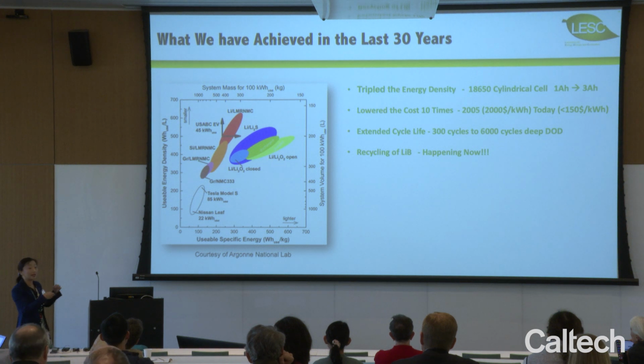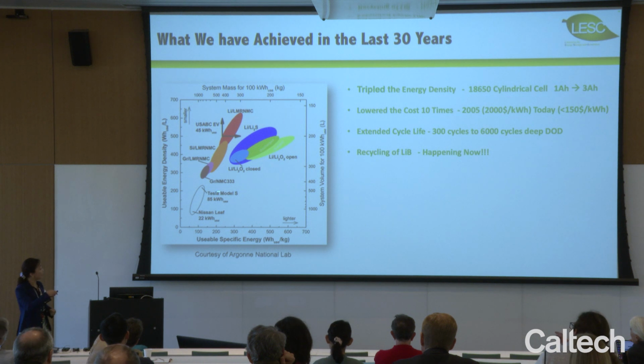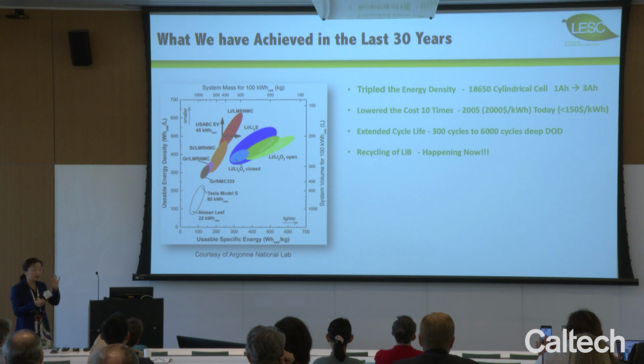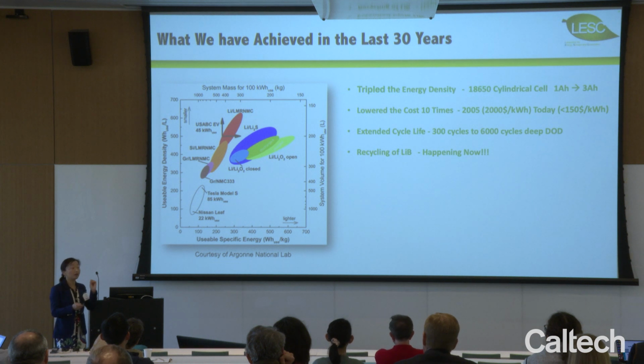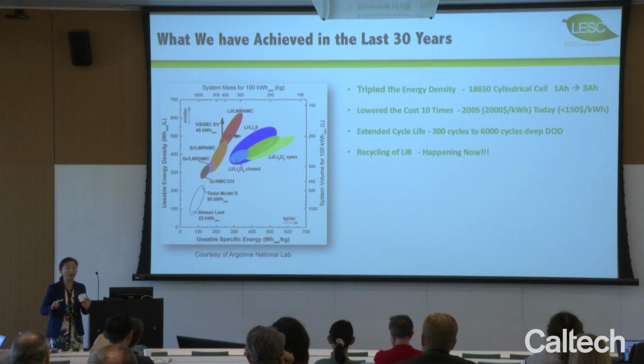So when we think about electric vehicles, typically volumetric energy density matters a lot. Now, when we think about flying drones, flying cars, we think the gravimetric energy density is more critical. And this map lays out clearly two very important research directions. One is that lithium metal as a holy grail must be enabled. And 50 years ago, in the 1970s, the first generation of rechargeable lithium metal batteries completely failed. Okay, completely. All the startup companies failed. And we have to do this again 50 years later.